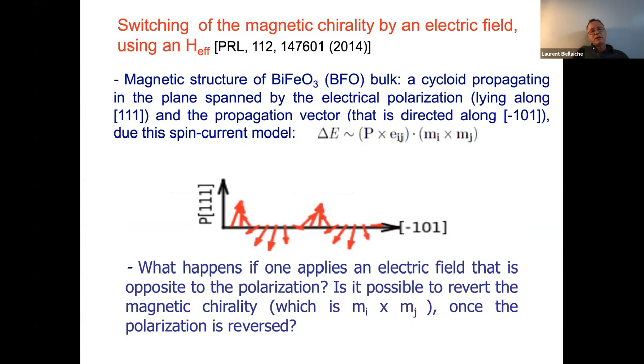This spin current model is absolutely responsible for the formation of a cycloid in bismuth ferrite. But if you pay close attention to this term, it is quite interesting, because M_i cross M_j is the magnetic chirality. So imagine you have a right-handed magnetic cycloid. Now if you apply an electric field and change your polarization from 1-1-1 to -1-1-1, this term is telling you that if you want to minimize the energy, as any system should do, you should change M_i cross M_j. It should go from plus to minus.